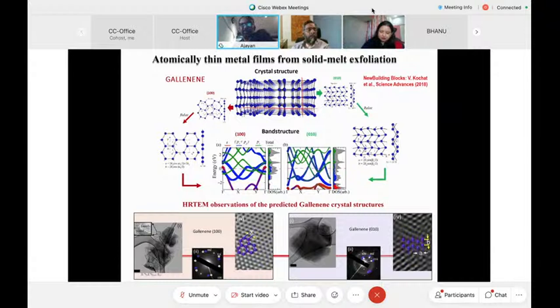And there are very many examples of variations on this exfoliation theme. This is another approach where we were able to pick up very thin layers of gallium using a slightly different method. We called it solid melt exfoliation. Gallium melts at a pretty reasonable temperature. Once it is in a molten stage, you can pick up very, very thin layers using some kind of stamping technique. And again, we could get layers as thin as a nanometer, very nicely crystallized on different substrates. Of course, gallium is a metal, and it still remains a metal when thin. But metallic structures are also important if you want to ultimately build devices, because you need good contacts, and gallium is a pretty good material because it melts and nicely forms a contact.